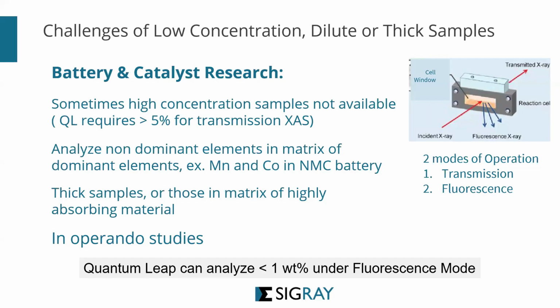So the Quantum Leap can analyze materials at less than 1% weight or 1% weight under the fluorescence mode. And we have done that to something as low as 0.2%.